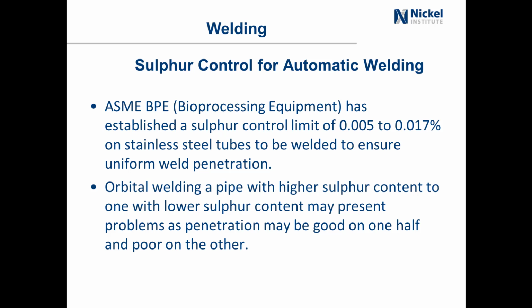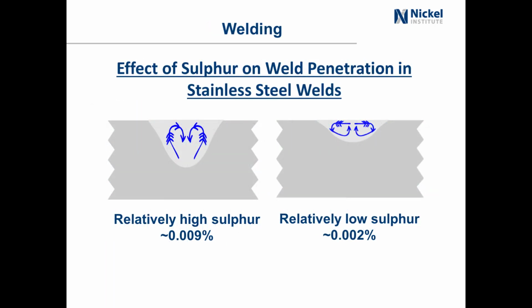But then when people started to do orbital welding, they found that they had a problem, and so they had to increase the sulfur content. And we can just see this in this diagram here. A higher sulfur content affects the circulation of the weld metal in the weld pool, so you get better penetration. And if you have a low sulfur, it doesn't go as deep. So it's just an interesting side note.